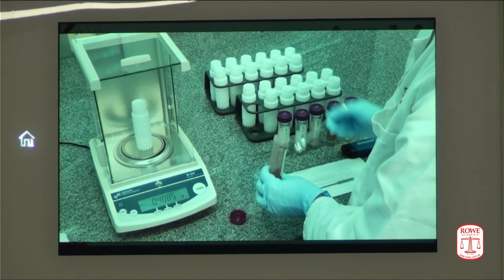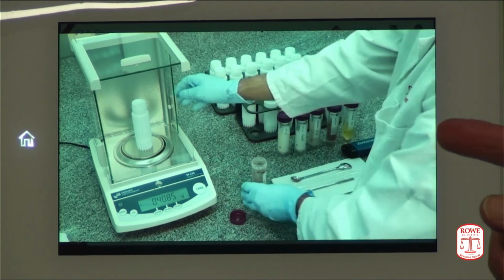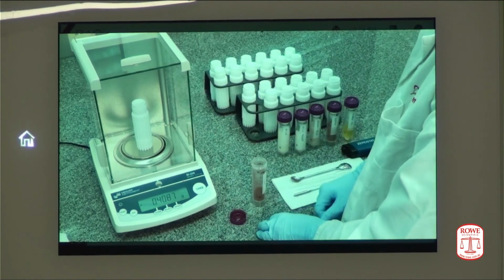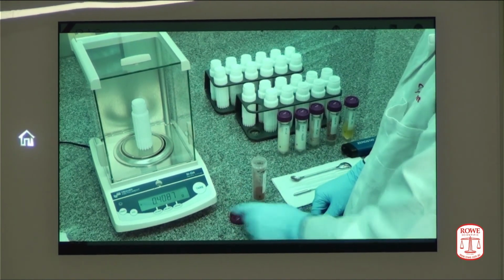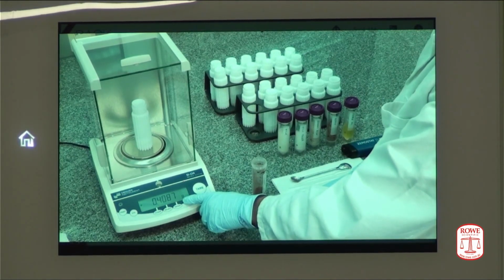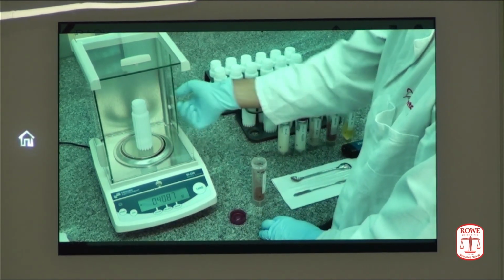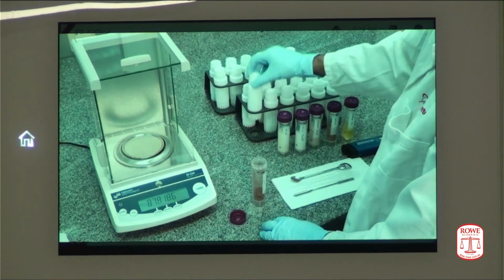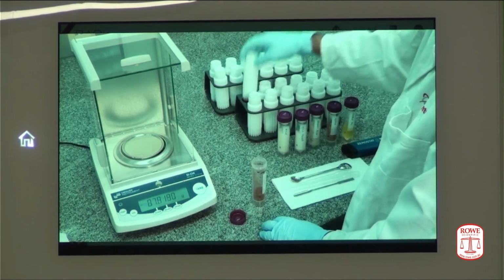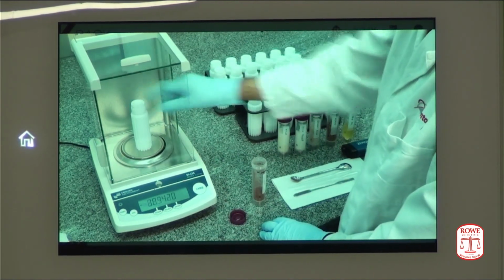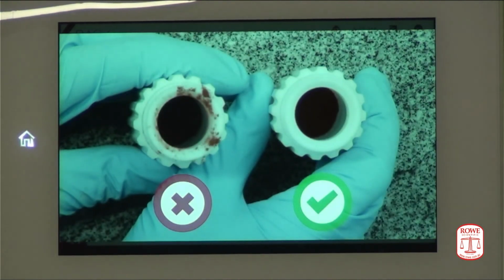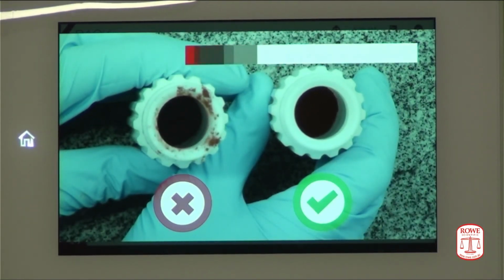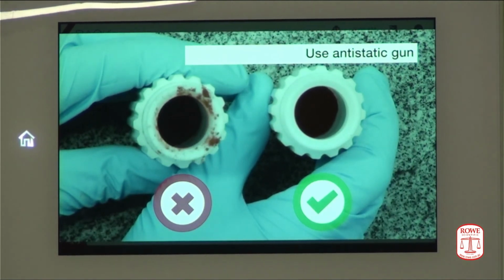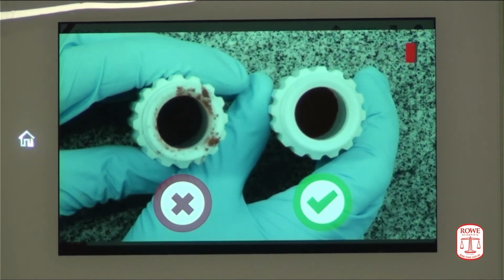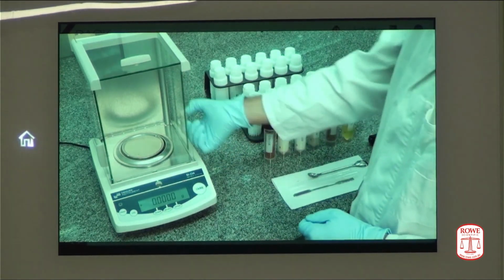Another thing is when you then, after loading, add the reagents, we recommend to turn the vials and to wash the sample material down into the solution. There shouldn't be any sample parts sticking to the wall when you start the microwave process. Yeah, this should not happen. That is what it should look like. Use anti-static gun. Things like that. Yeah, that's good.